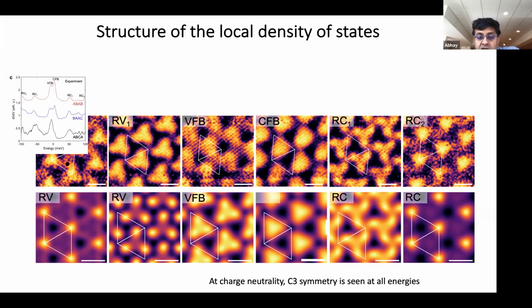Okay, so this is a picture of the local density of states of this system exactly at charge neutrality. And at charge neutrality, no matter which energy you look at, you can see threefold rotational symmetry everywhere. Right? So now we play the usual game. We apply a gate voltage and we dope the system, and we ask what happens to all of these wave functions as you start to dope the system.